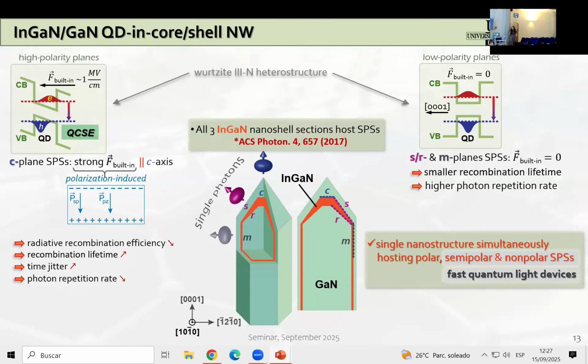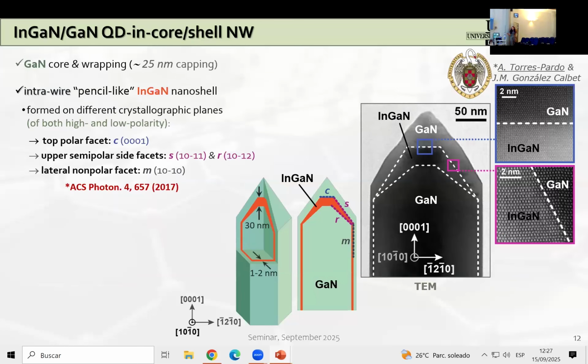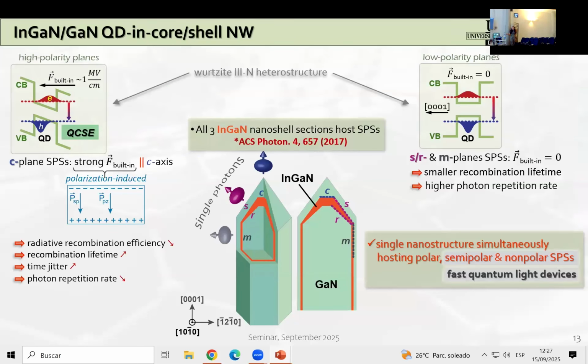So what we have shown in this publication is that our nanowires are actually the first experimentally demonstrated nanostructures capable of simultaneously hosting quantum emitters with different crystallographic orientations. Now, as I will show later, all three sections of this InGaN nanoshell contain quantum dots, which are responsible for the emission of single photons.